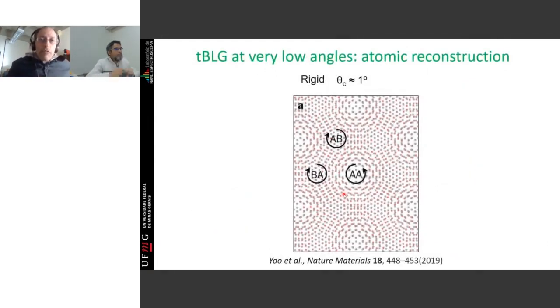And one last piece of information about this topic. Here I represent with red and gray bullets the top and bottom layers, okay? Where I name AA here is when the top layer falls exactly on top of the bottom layer. So one atom falls on top of the other. Here where I call AB is the same situation I told you before, where you have one atom of the top exactly at the center of the hexagon from the bottom. And if I look here, let's say that the gray atom will be in the middle. If the red atom is in the middle, I will call it AB and BA, okay?